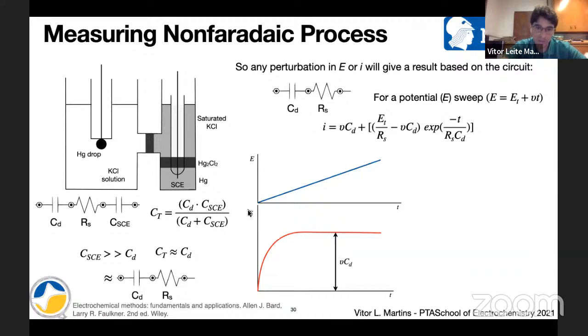So potential is increasing because we told the potential to start to increase at this rate. And here you are measuring current. Sorry, here is wrong, it's current. You are measuring current over time. So we have exponential growth in smaller time, and then when time keeps increasing, we have a constant value that will be related with the capacitance of this capacitor of the electrode, right? And the scan rate. So it's a product of the scan rate and the capacitance.